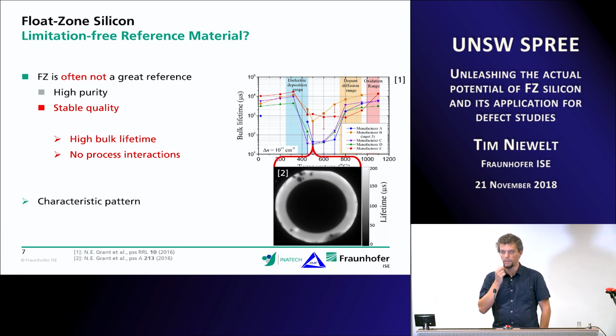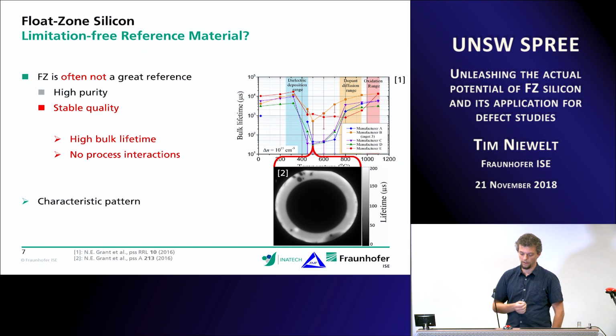The good thing is this effect that Nick has been seeing is quite characteristic. So when we take a PL image of a wafer that's strongly affected by that, they usually look like this. So if intensity here is giving us a direct measure of the lifetime, then we see that the lifetime is quite good at the edges of the wafer. There is a good rim of lifetime, and then the lifetime drops significantly, and we have this circle shape in the middle of a really bad lifetime.